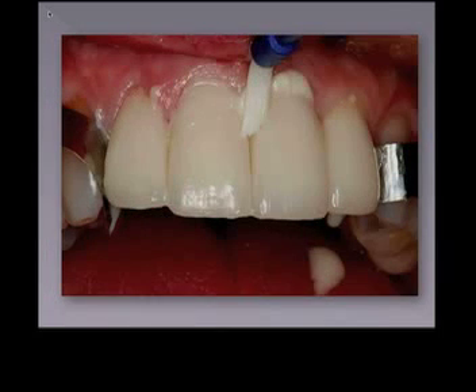Dual Link is allowed to gel for 30 to 60 seconds. Scalpel excess removal followed by appropriate light curing. I just find that a sickle instrument takes this off very, very easily, and the cleanup is just a dream. I really have no problem cleaning this up.